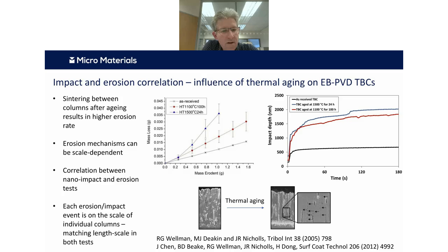And what they found was that after thermal aging, the erosion resistance of these TBCs decreased. And when they looked under the microscope, in cross-section, they found that this was due to sintering, both between the columns and within the columns. And this ultimately led to the possibility of more material being removed per impact, and cracks that form subsurface would then be able to travel more effectively across columns. So some of the strain tolerance in the system was being lost.